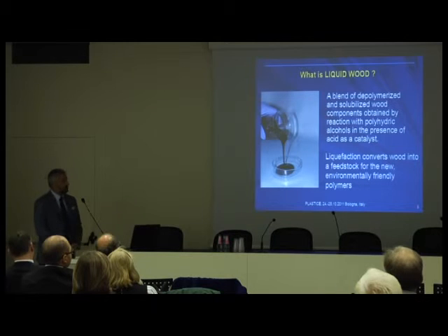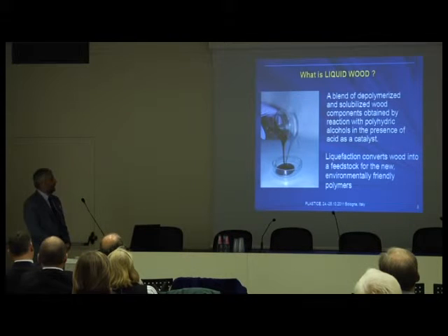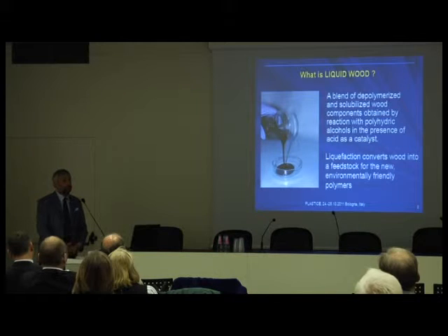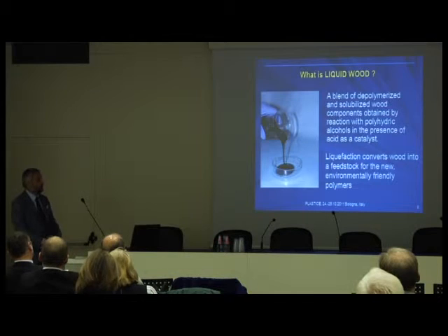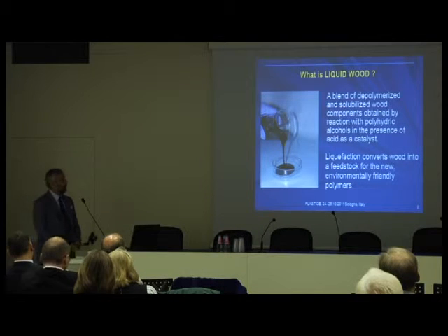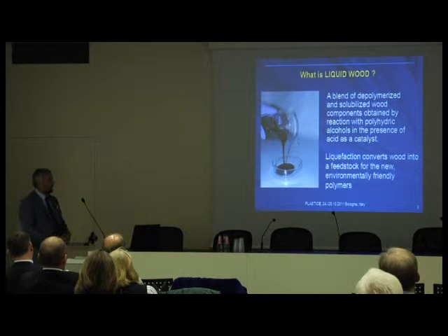What is the product? As you can see from this slide, it is a dark brown liquid with about 3 kilopascal-seconds viscosity and with a lot of hydroxyl groups available for further reactions. And that is the beauty of the product, because these hydroxyl groups can be used in polyester synthesis, in polyurethane chemistry, and some other applications.